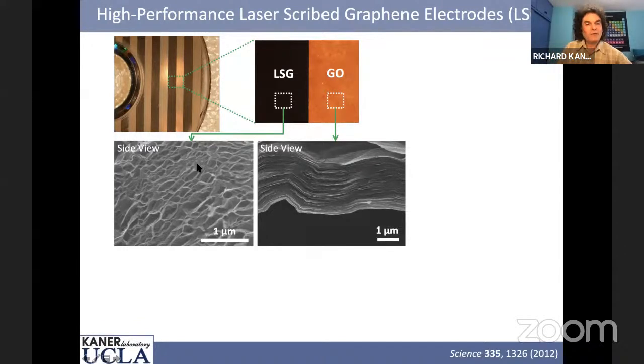How do we know that? Well, because we can look at several different attributes. And this is a graphene, but it's the world's most effective form of graphene. Now, why do I say it's graphene? Well, graphene has 3 attributes. It has high conductivity, which we can measure. This has high conductivity. It has high surface area, in theory, 2,630 meters squared per gram, where our material has somewhere between 1,500 and 2,000 meters squared per gram.